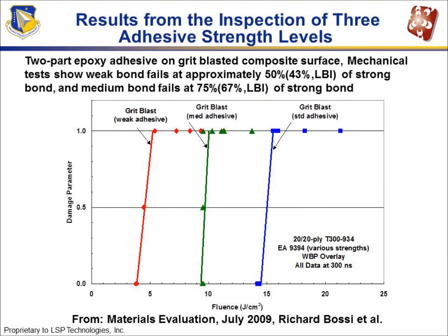Boeing did some mechanical testing on these and found that the mechanical strength broke around 50% of the bond strength of the strong bond. The middle adhesive broke about 75%. With LBI, we detected about a 43% threshold, and for the medium bond, we detected 67%. So there's a good agreement between what laser bond inspection is telling you and what's happening mechanically.